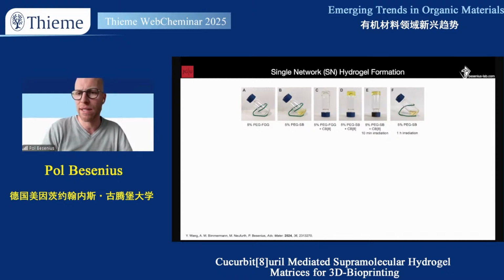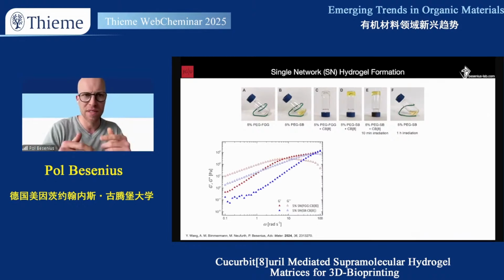The peculiar thing is if you take the stilbazolium unit on the PEG and you hit it with light for 1 hour, that doesn't seem to be long enough to get an effect, because you can extract a little bit on the time scales of that dynamic exchange from rheology, which turns out to be very important information. If you look at the red data points, G prime and G double prime, storage and loss modulus, as soon as they start to cross, shown here as the crossing point in the frequency sweep in shear rheology, this gives you an idea about the lifetime of that supramolecular connectivity or the supramolecular bond. That's something that I already gave away on the introduction slides, about 100 milliseconds as critical lifetime.